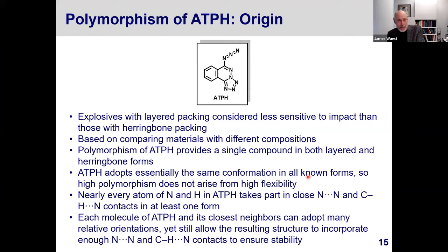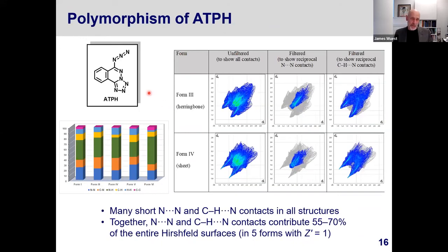So that's sort of an assessment that's highly qualitative. It's based on looking at the crystal structures, and it can be supported to some extent by quantitative measurements such as an analysis of Hirshfeld surfaces. You can see from the chart here that there are a large number of NN and CHN contacts in all the structures. In fact, these contacts contribute 55 to 70% of the entire Hirshfeld surfaces.